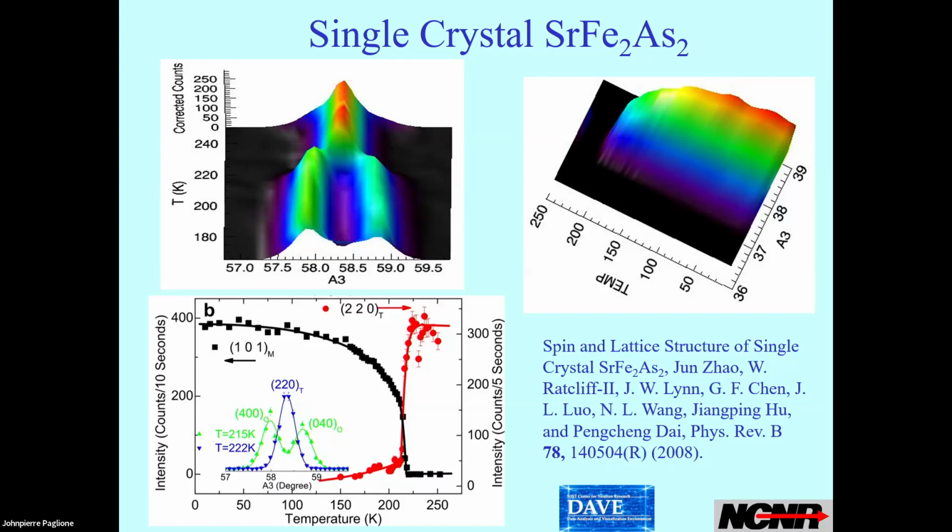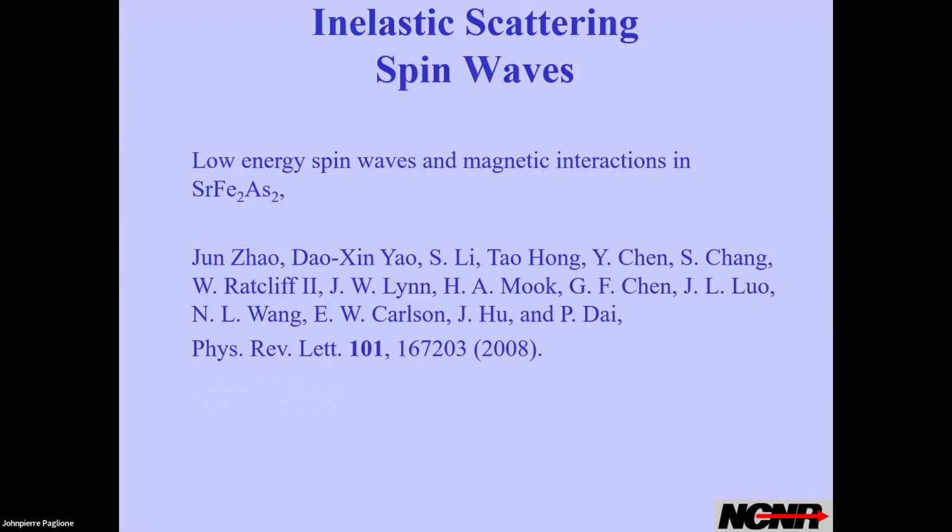And the reason for that is that if you put a powder up there, the bright peaks that you see only come from a few of the grains, right? It just happens that if you're at a particular powder diffraction peak, there may be 100 grains that are actually Bragg scattering. The rest of them are just sitting there. And what are they doing? They're causing background. So that's basically why single crystals typically get much better data.